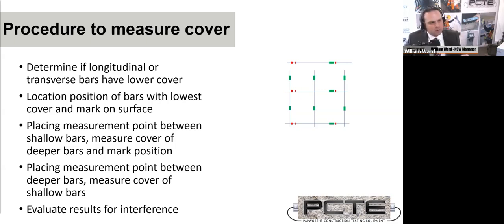Now, if this was a very critical cover survey and it was, for example, for input to a durability analysis, there is often also scope to confirm that your cover meter is reading your cover depths correctly after following this procedure. With any NDT technique, a couple of points of destructive testing can really back up well a report for critical matters. But with this procedure, you should have a very good cover depth measurement. If you know the bars, it should be an excellent cover depth measurement. And maybe there's scope to do destructive investigation to get that bar depth and to confirm the function of your cover meter, where the job is absolutely critical. And this is universal on any NDT technique, you can really make it almost a certainty if you've got some destructive evidence to back up your non-destructive evidence.